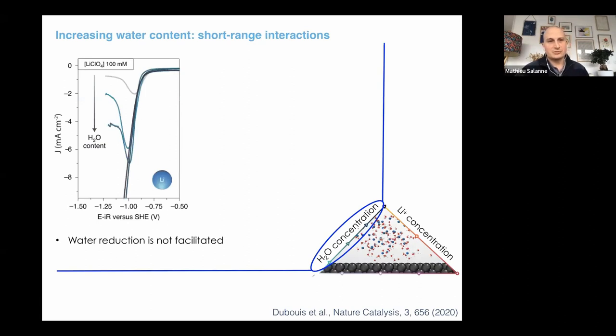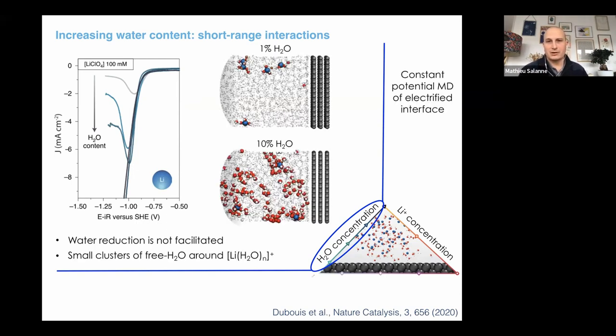So the first step was to start from a very dilute solution and increase the water concentration. And so on the left here, you have the electrochemical response. So you see that the behavior is a bit different because you pass from a peak to a wave, but this is due to some surface effects and surface passivation that can occur. But the important thing is that the potential at which the reaction is triggered does not change. So it means that starting from the initial system, increasing the amount of water does not lead to an enhanced reactivity.